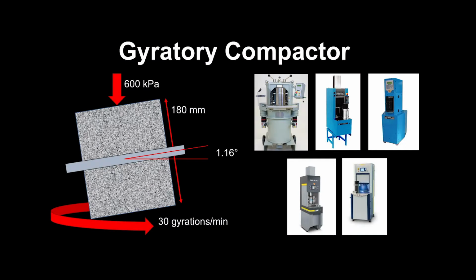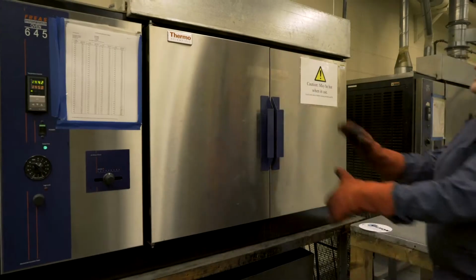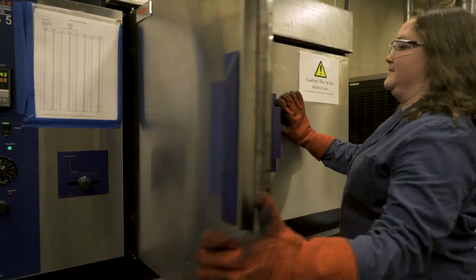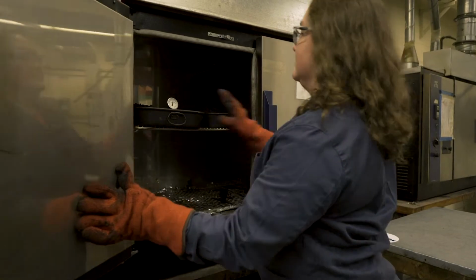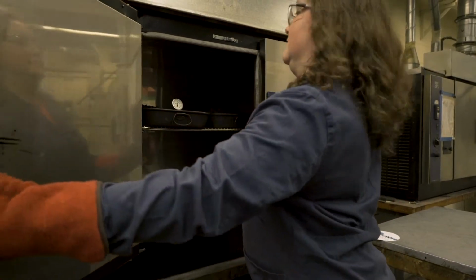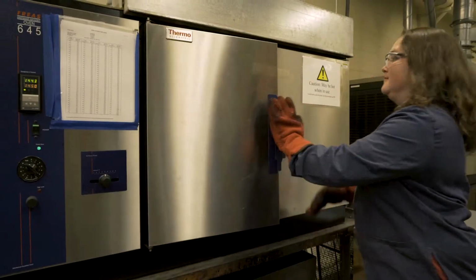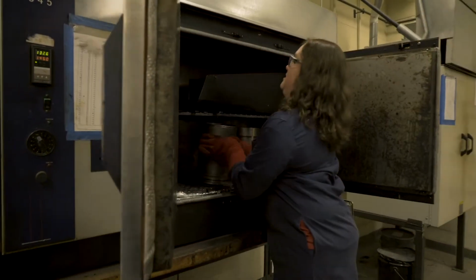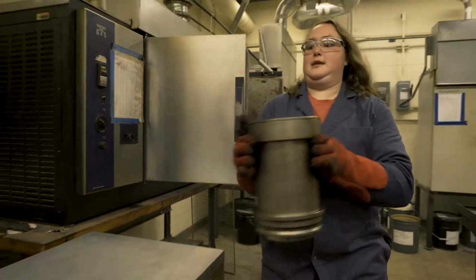Set up the gyratory compactor to compact samples to a height of 180 mm using a rate of 30 gyrations per minute, an internal angle of 1.16 degrees, and a compaction pressure of 600 kPa. Check the temperature of the mixture regularly to determine when the compaction temperature has been reached. This time is typically around 30 minutes to 1 hour. Once the appropriate temperature is reached, remove a compaction mold, the transfer device or scoops, and spatula from the oven.